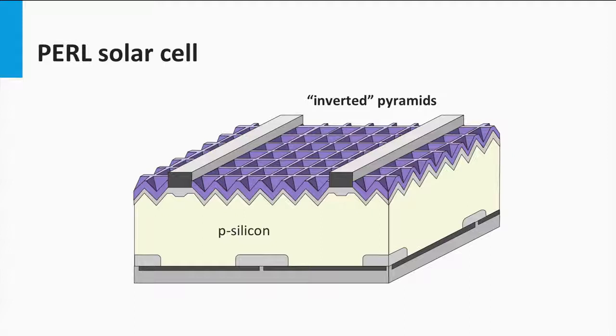Secondly, the inverted pyramid structures are covered by a double layer anti-reflection coating, which results in an extremely low top surface reflection. Often, a double layer coating of magnesium fluoride and zinc sulfide is used as an anti-reflection coating.